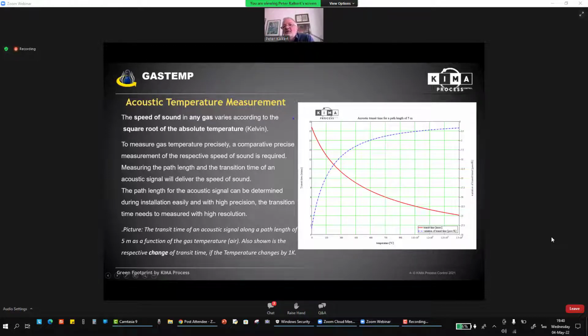For example, what you see here is the calculated transition time of an acoustic signal that is passing the duct of a diameter of 5 meters. You see it? The red curve shows what is the transition time for an acoustic signal when it's passing this 5 meters as a function of the temperature. And you see, we start with around 15 milliseconds and we end up somewhere in the range of 6 milliseconds if we have a temperature around 1,500 degrees centigrade.